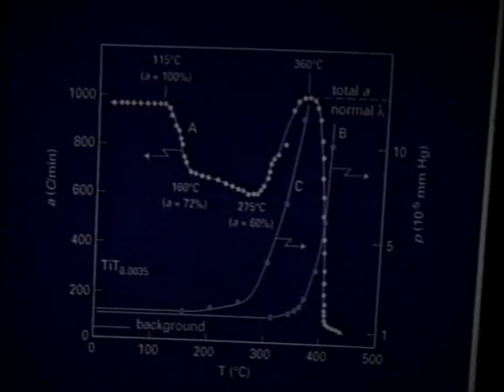The increase of the radioactivity just started at the same temperature as the increase of pressure at the second rise of temperature. We arrived at the preliminary conclusion that this is the temperature where the tritium atoms lose their bonds to the titanium lattice. From this coincidence, we arrive at the preliminary conclusion that the binding of the tritium atoms to the titanium lattice is a necessary condition for the decrease of lambda.